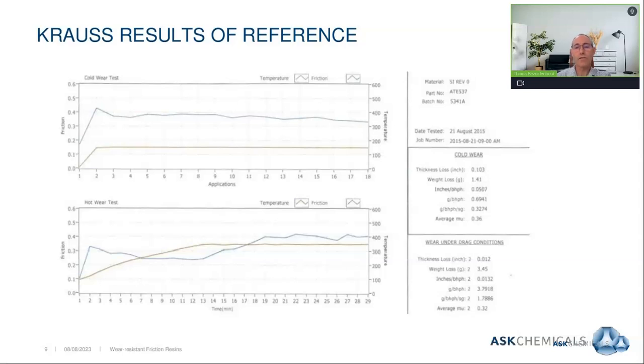On the right hand side, again, if you follow my pointer, we express the wear as grams per brake horsepower hour per specific gravity, and in this case, we obtained a number of 0.32 under cold conditions. In other words, 150 degrees Celsius. If we look at the wear under hot conditions or 350 degrees Celsius, what we call drag conditions, the wear gives us a number of 1.79, and we'll keep these two numbers in mind as we now look at the comparison with the new technology. We'll keep in mind 0.32 and 1.79.